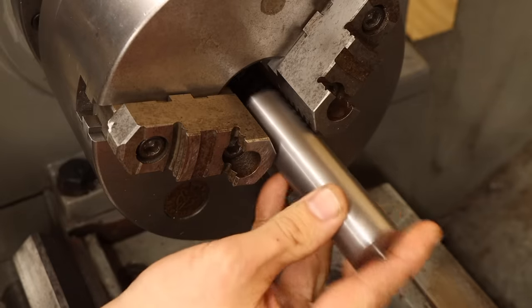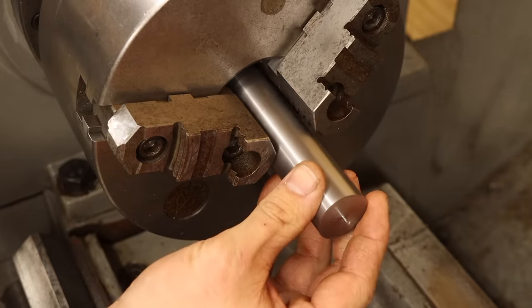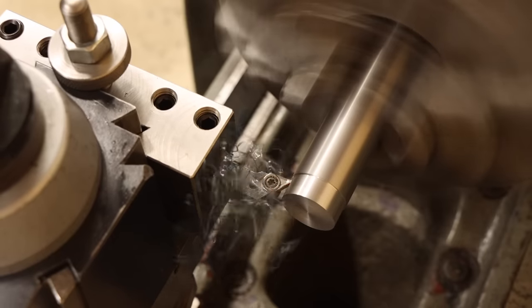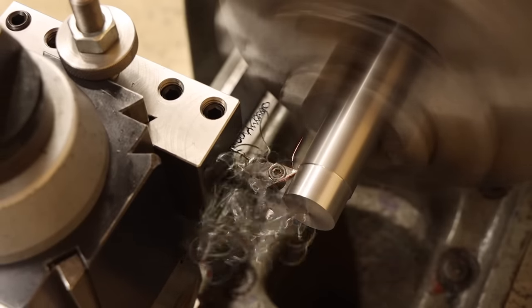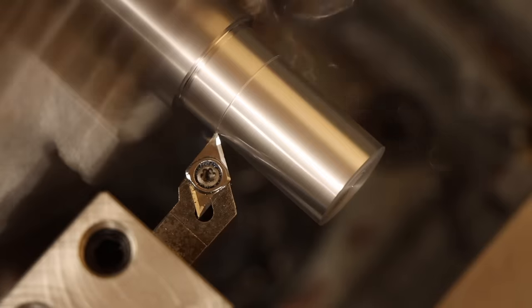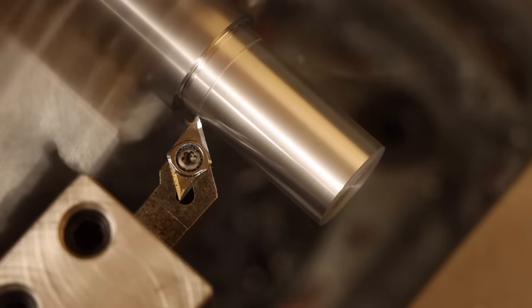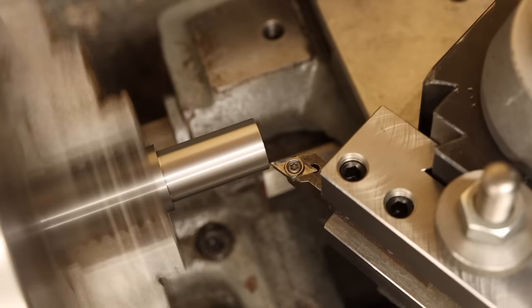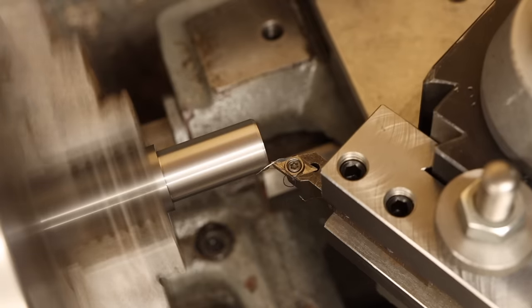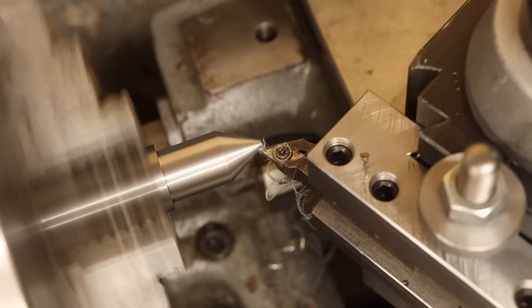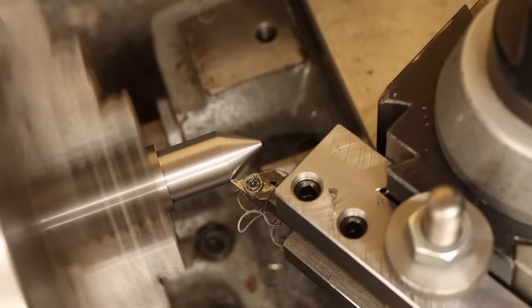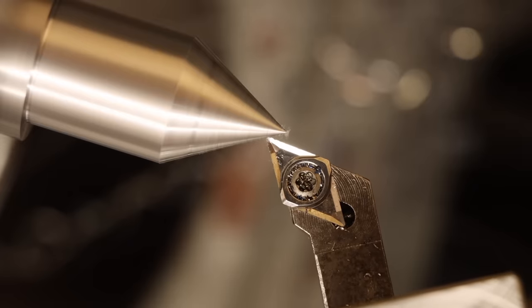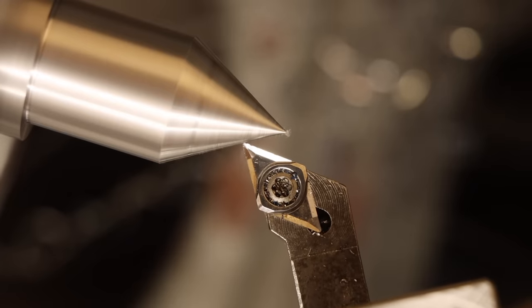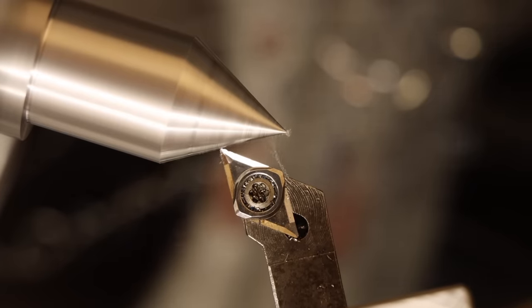I'm changing materials here and going with some O1 tool steel. This will give me the option to harden, like most live centers are, but I won't actually be doing that at this point. The difficulty with heat treating is that it turns straight parts into bananas. You can grind those bananas back into straight parts, but at the moment I have no cylindrical grinding equipment. So for now, no hardening. Sure, it's a bit of a cart before the horse situation, but I'm an excitable child, so we're going to keep going.